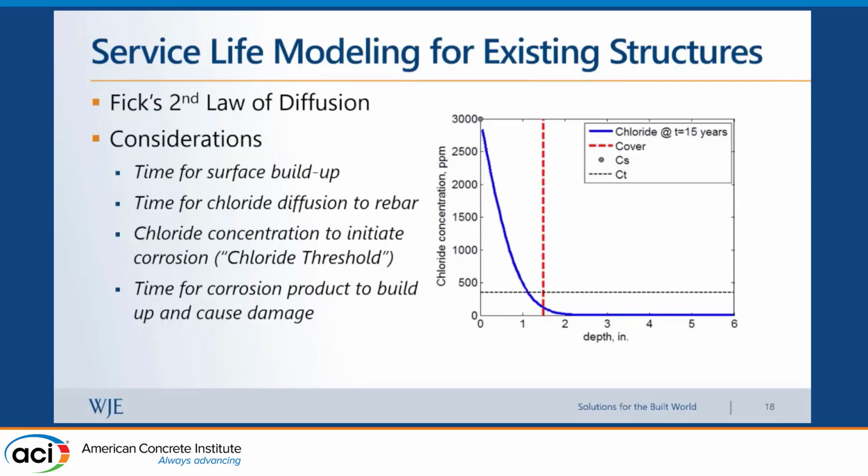And this is based on Fick's second law of diffusion, which considers the time it would take for the chlorides to build up at the surface, and then how long it would take to diffuse over the concrete cover until it reaches the bar, and then accumulate at the bar depth to a concentration that we call chloride threshold. And this is when we consider corrosion initiation happens, and the corrosion of the bar starts.